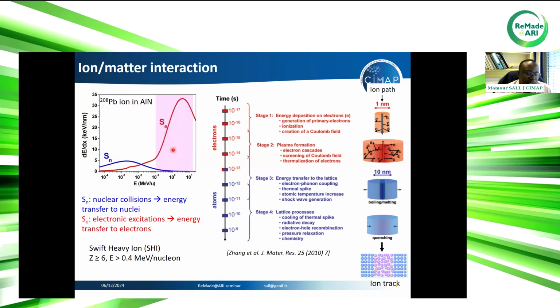And as I said before, in this energy loss range, defect creation is an indirect process because the energy of the ion, the projectile, is transferred to the electrons, and then it will be transferred to the lattice for creating defects. Typically, this is what will happen. We have an ion entering the material here. Around this trajectory, it will excite delta electrons. These delta electrons will create an electron cascade, and then the energy from the electronic subsystem will be transferred to the lattice subsystem, to the atomic subsystem.